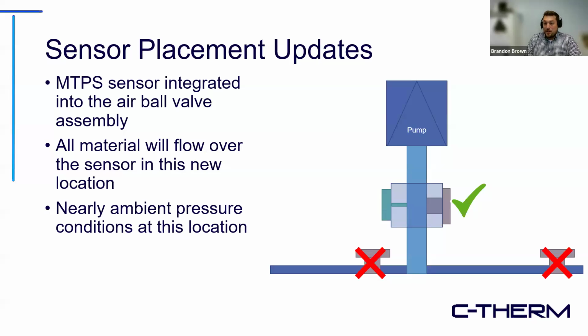One of the big benefits to measuring on the following plate is that the pressure was very near ambient in the bdtronic equipment, and we're able to get a good reading on the top layer. However, not all the material passed over the one spot on the top plate, because if you're measuring an area and you're measuring here, the material on this side doesn't flow over it. Another location we tested with great success was just at a valve, right just below the pump. This again had the benefit of being at near ambient pressure conditions, but also all the material to be processed would be passing through this point.